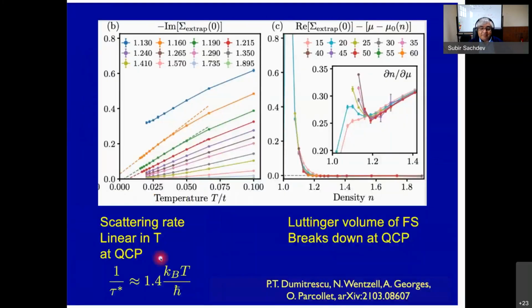They also measured the Fermi surface, or the Fermi energy, really. This is a random system. And again, they find that in the higher doping regime, you have Fermi liquid behavior, and that totally breaks down once you enter the spin glass phase. And what they were also able to measure is the scattering time of the electrons, which was what was measured in the experiment that I showed you in the beginning.